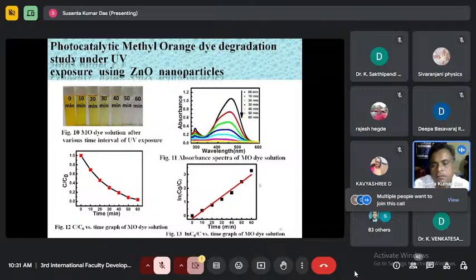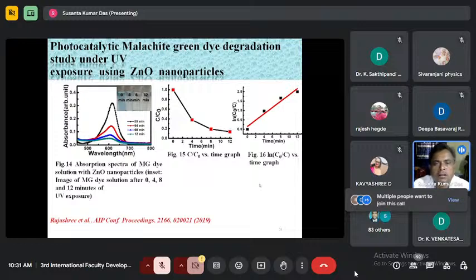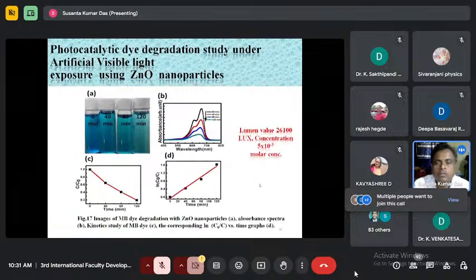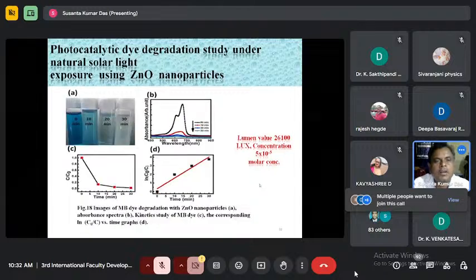You can see we got similar results. Then we had also done for other dyes like malachite green, and then we switched to the visible light source also, and we found good results. In this case, we had not found that much significant result. You can see, because zinc oxide is a wide band gap material, there was some decomposition, but it was not as high as UV light decomposition. But when we did the experiment with solar radiation, we got good results. Within 30 minutes, we got the decomposition, as you can see here, and the origin is obvious.